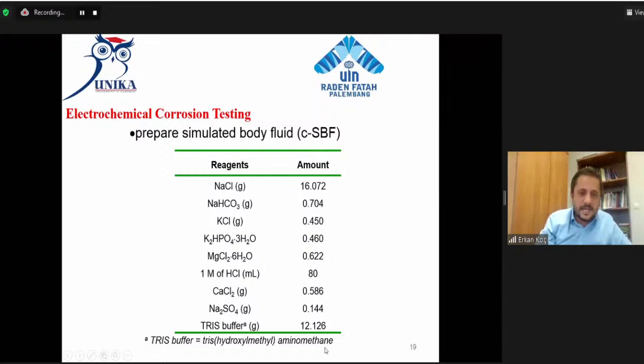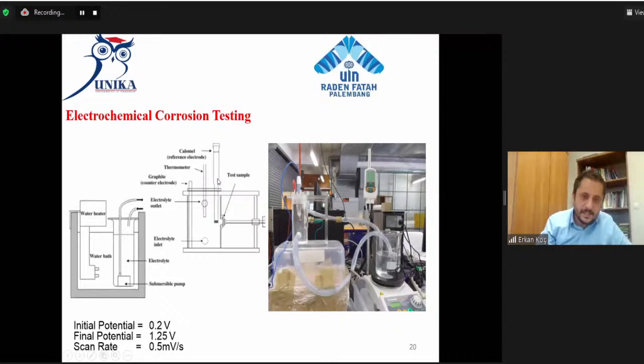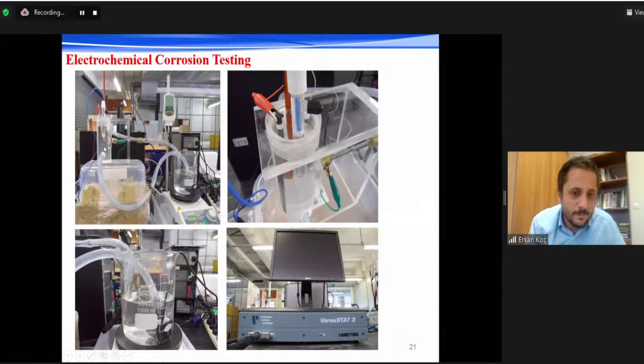A typical 3-electrode system consisting of graphite here as a counter electrode, silver chloride or calomel electrode as a reference electrode, and the sample. Here is the sample. Experiments: potentiodynamic electrochemical corrosion test, always circulating. You know, our body always has circulating fluids, so we have to use circulating flow in the experiments. Here is the pumping, and then it is always circulating.